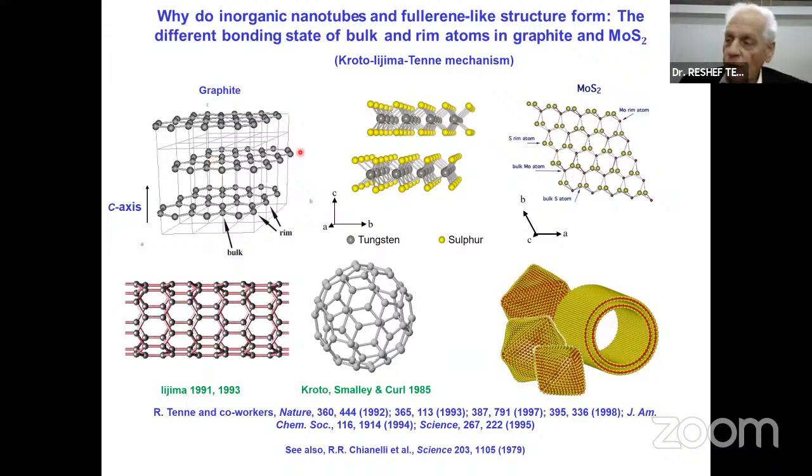And if they are twofold bonded, they will not be stable, especially when you go to the nanostructure, when you have so much surface or so many edges, and the material will close and form fullerenes. It pays from an energetic point of view to impose a strain and fold and form a hollow closed structure, and pay the price of this elastic energy by annealing these dangling bonds.